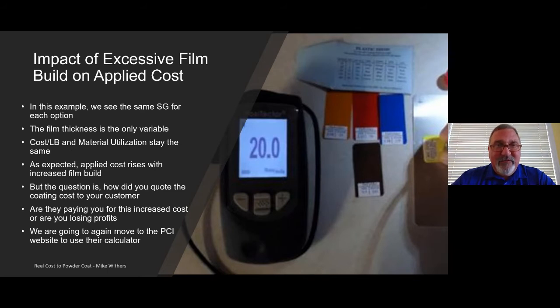But it obviously makes sense that if you put more on than is required, then you're going to be increasing your cost. Well, the TDS also tells you the recommended film thickness from the manufacturer. And so if you've got a recommended film thickness of 2 to 3, and the sweet spot in the middle is 2.5 mils, and you're able to control that versus someone who is putting on 3.5 mils, then you've got an opportunity to have a lower cost. So the film thickness is going to be the only variable. Cost per pound, material utilization, everything's going to stay the same. And then we're going to look at how that impacts the cost.